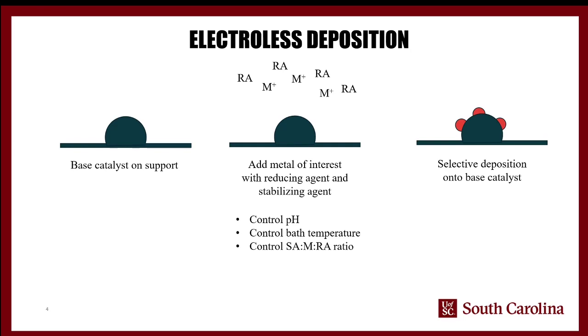The ratio of those determines how quickly the reduction happens, and so you need to find that happy medium between a reduction that takes too long and a reduction that occurs so quickly that you end up with large nanoparticles that you can't control the size of very easily. If you control it very well, you can dictate very selectively the size of the nanoparticles that are formed by controlling the rate of the reaction.